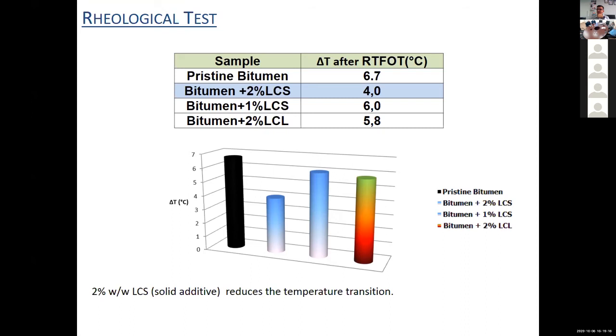In this result, we observe that the pristine bitumen, when aged, shows a higher transition temperature, around 6.7 degrees, in comparison with the pristine bitumen not aged. We have the best results when 2% of the solid additive is added to the bitumen. In fact, the shift of transition temperature after aging is lowest. So the use of this additive reduces the aging of the binder, extending the life of the road pavements. In this case, only the solid additive can be considered a good antioxidant agent because the liquid additive does not show significant improvements.